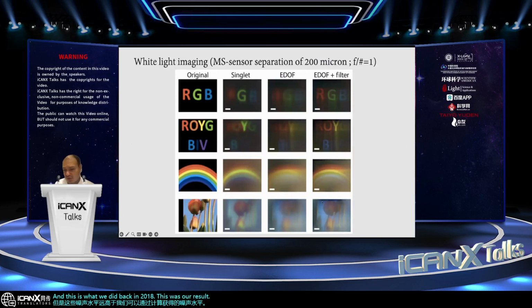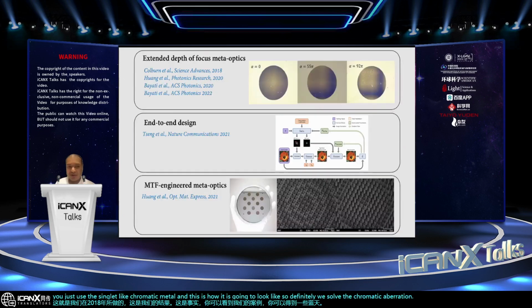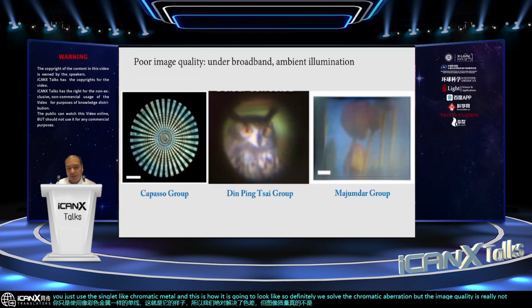You can see with our case, we can get a somewhat blue sky, some stems. If you just use the singlet chromatic meta lens, this is how it's going to look. So definitely we solved the chromatic aberration, but the image quality is really not there. And this has been a problem. If you look into the imaging that people have done back in 2018, some chromatic aberrations are solved, but the imaging quality was not there.